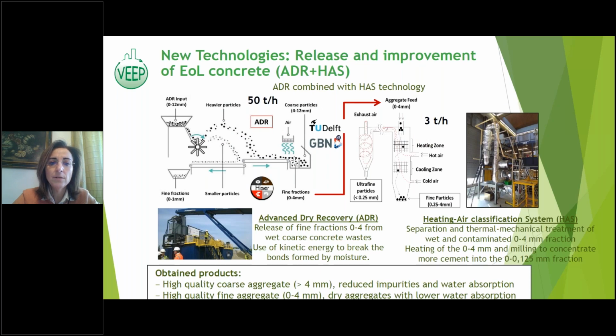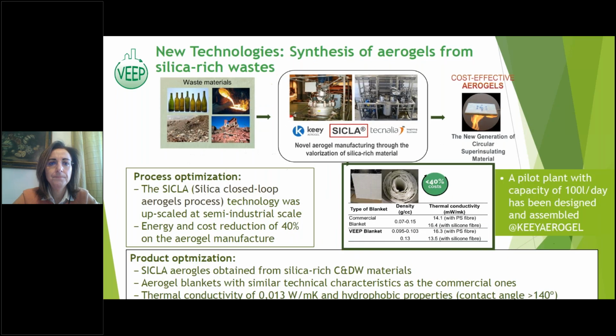In particular, at the beginning of the project, we went through the design and development of 2 systems, the ADR and the HAS, which are capable to treat the coarse and fine fraction of the recycled concrete aggregate. Adopting these 2 technologies, we were able to achieve high quality coarse and fine aggregates. In terms of technologies, we have also developed a pilot plant with a capacity of 100 liters per day for producing a green aerogel. The green aerogel is characterized by a very low thermal conductivity and hydrophobic properties, but with a cost reduction of more than 40% with respect to the state-of-the-art aerogel.